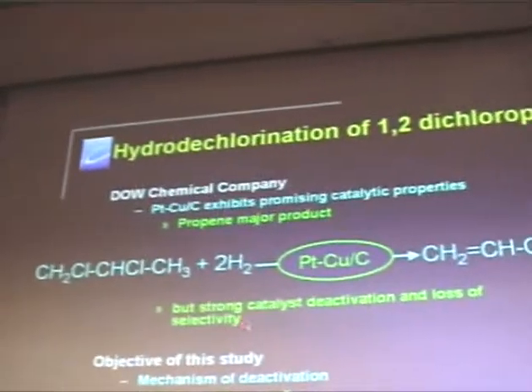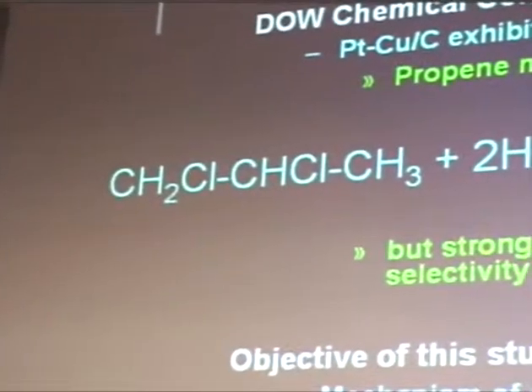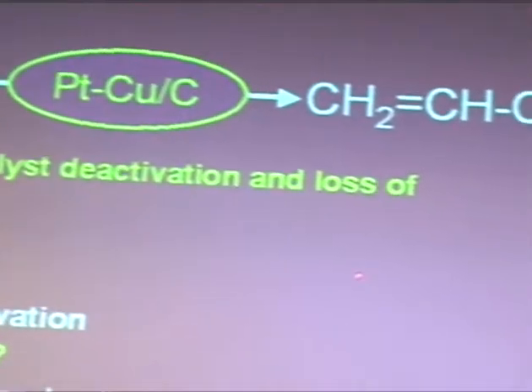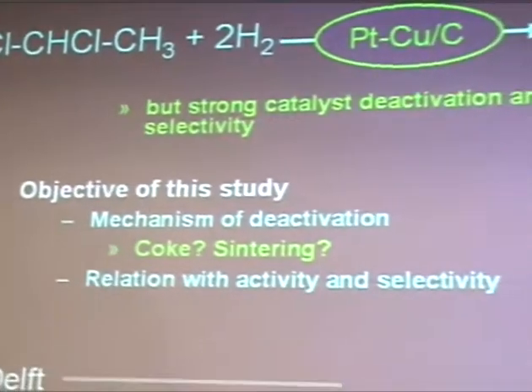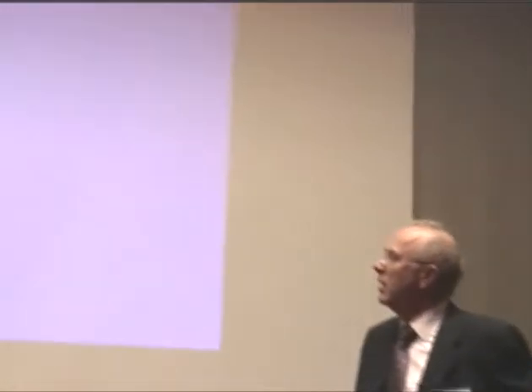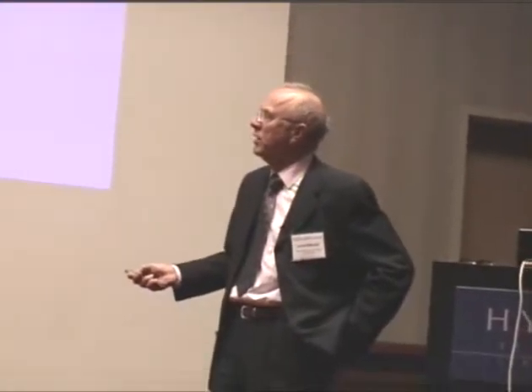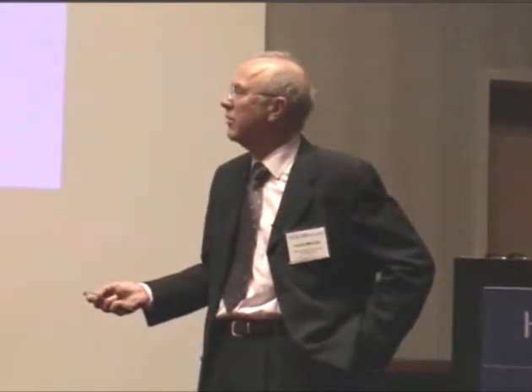And there was only one big problem. The catalysts show strong deactivation and loss of selectivity. That means that at a certain moment you make more single chlorinated products than chlorine-free products. That's a very important point. What we want to do is we want to elucidate the mechanism of deactivation. Is coke the major point? Might sintering play a role? And after Gustavo this morning, I shouldn't talk about it probably anymore, but you'll see we conclude that sintering is not a point here. And is there a relation with activity and selectivity?